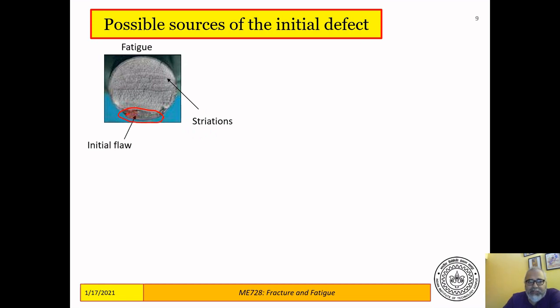So this was the initial flaw, and then as the shaft was being used, it grew by a little bit every time the shaft was operated. And these marks that you see here, very closely spaced, you can hardly see them. These marks are called striation marks, which indicate every step the crack was taking as the shaft was being operated.